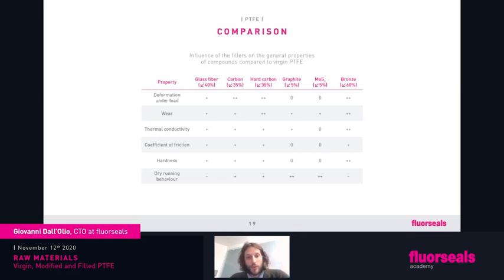Thermal conductivity is usually always improved because PTFE is a thermal insulation material, a very good insulant. So when we add something that has a better thermal behavior than PTFE, almost anything that we add to the PTFE will improve the thermal conductivity. And going back to the dry running behavior, we mentioned two products, the MoS2, moly, or the graphite. Those are the go-to fillers for dynamic application in a dry environment, so when we don't have lubricants.